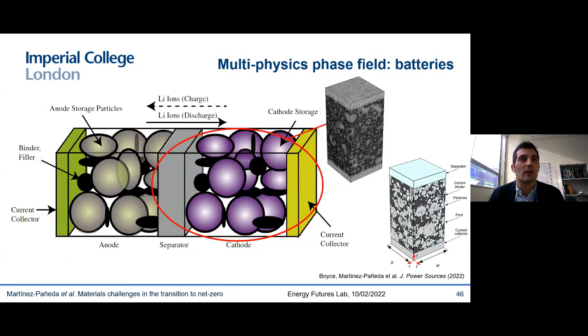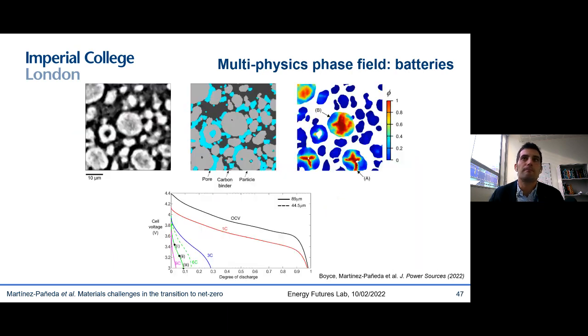On another front, and this is together with Adam and colleagues at UCL, we have gone one step further, and for the first time we have been able to model the entire cathode. And we do this by combining multi-physics phase field fracture models, similar to the ones you've seen before, with advanced X-ray computed tomography imaging. And this allows us to evaluate the influence of different phases, like binders or pores, and also explore the role of cell characteristics like electrode thickness, for example.